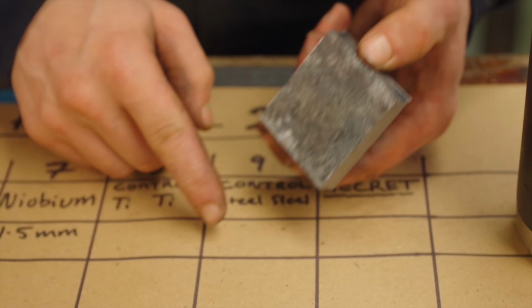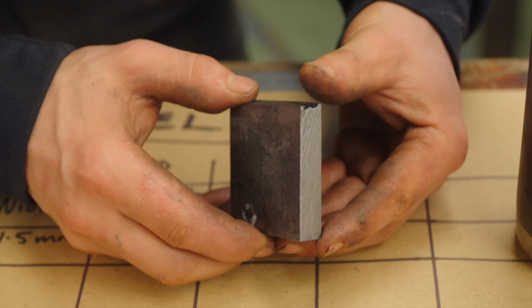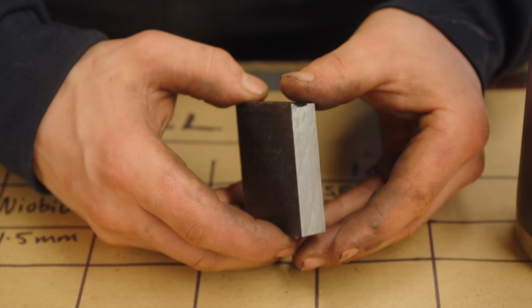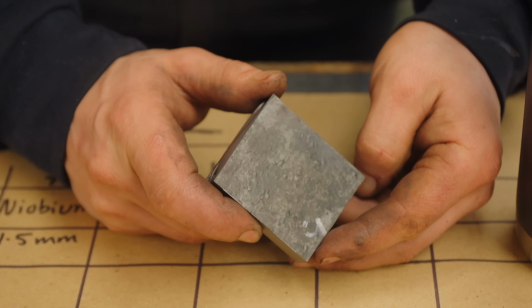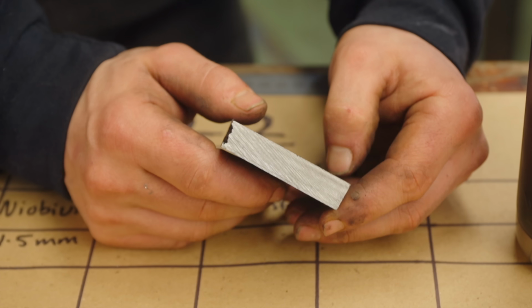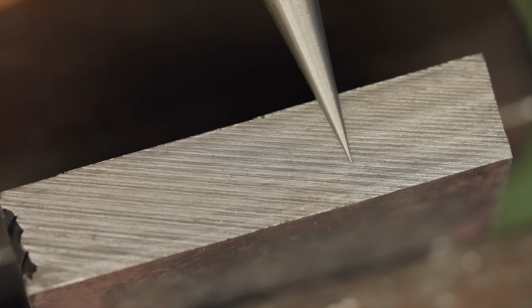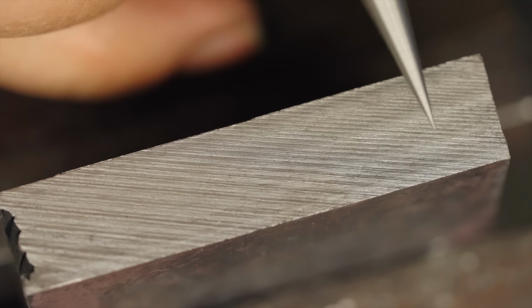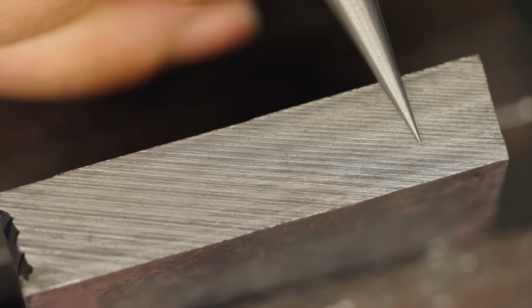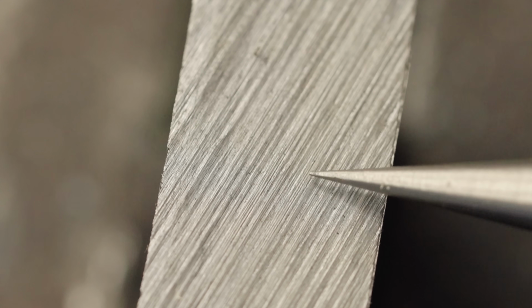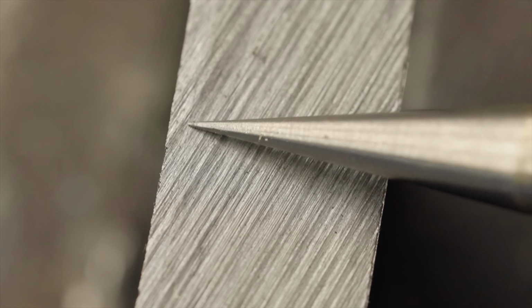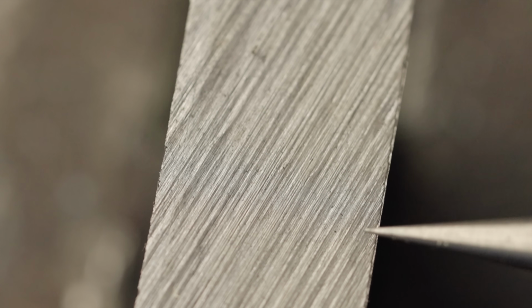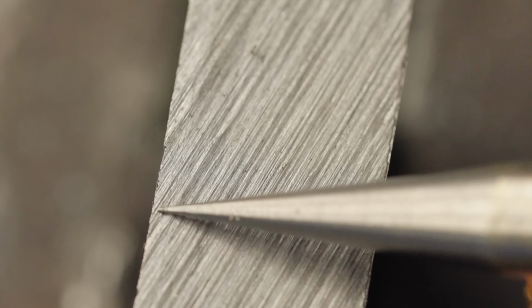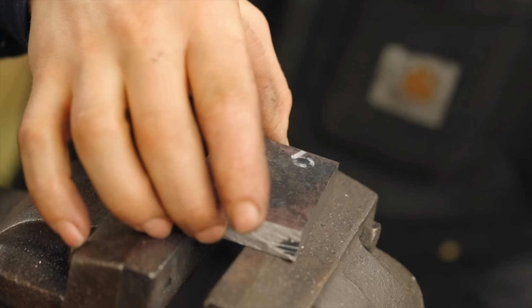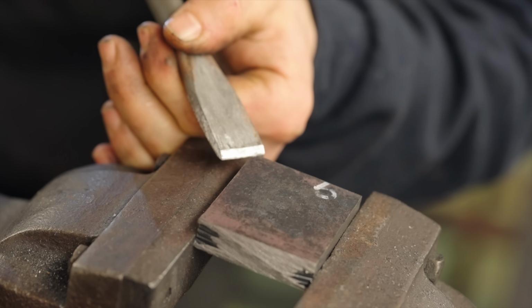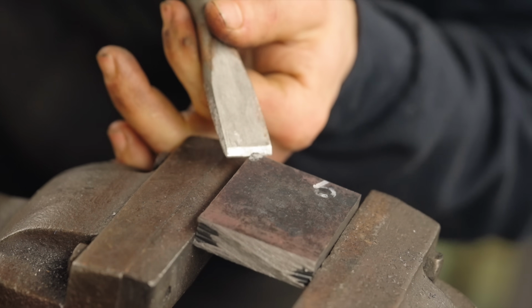Before we take the jacket off of this, billet 9, our control, steel, remember that what we're looking at is steel that has been forge welded or diffusion bonded at 850 degrees Celsius. Orders of magnitude lower temperature than I have ever welded steel before, and I am completely shocked that this is possible. I didn't believe in the slightest that this was going to work. But what this tells me is that in a good enough atmosphere, with as little oxidation as possible, remarkable things are possible. However, just looking at it visually, I don't know if you can see, but to me, it looks like you can see a little line at the joint between the steel box that we bonded to the 1080 that did not have the same rigorous surface grinding and cleaning done to it. And so, if I can break that mild steel box off, it tells me that provided you clean well enough, you can do crazy low temperature forge welds in steel.